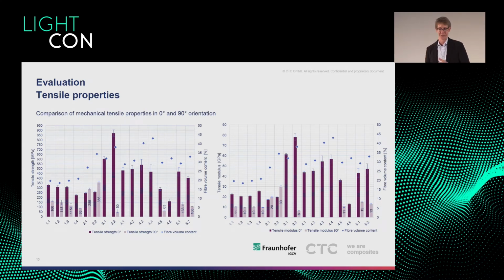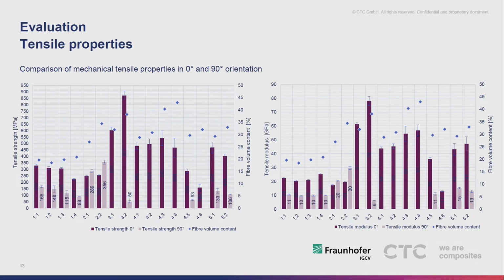And by far the best candidates, all technologies on the right-hand side of this graph, are more directed in the subsequent stretching. With some of those, we had adherence issues between textile and the resin. That's the candidate 4.6, where we actually didn't really measure the fiber and the performance of the coupon, but we measured the lack of adherence of resin to the fiber, which is going to be a completely different story in terms of sizing of pyrolyzed and recycled fibers. But you very obviously see one candidate that is standing out far, far beyond the others.